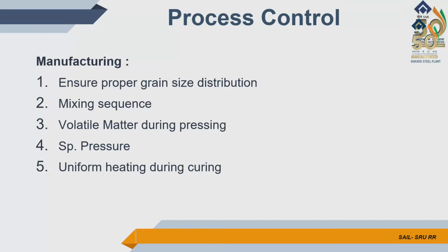Volatile matter was an issue. Higher volatile matter will lead to cracking in bricks. Lower volatile matter will leave the brick with high pores, so bulk density will be reduced. So we have to have a good volatile matter control. 1 to 1.4% is the current norm.